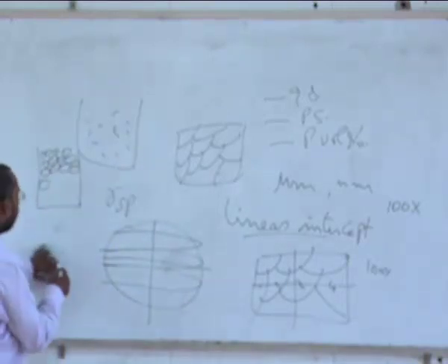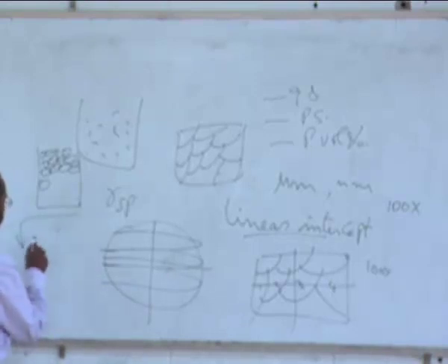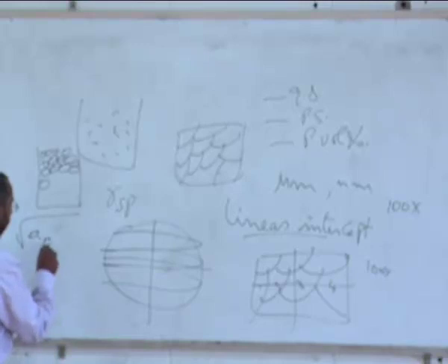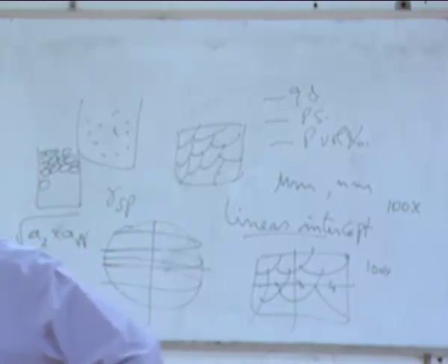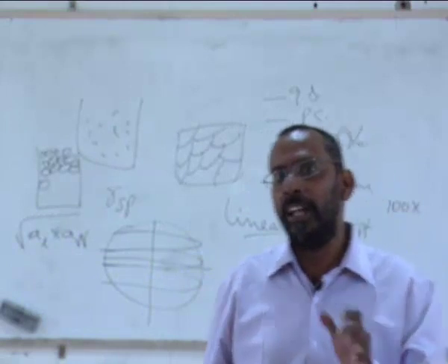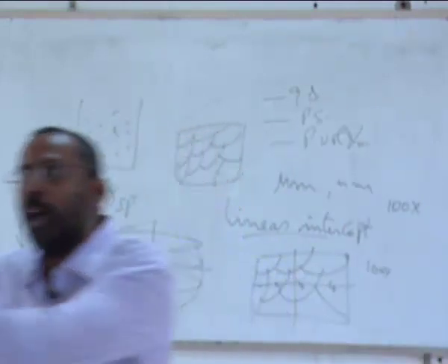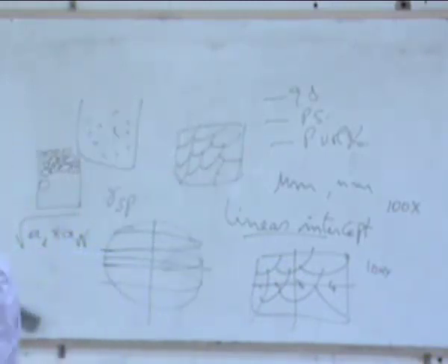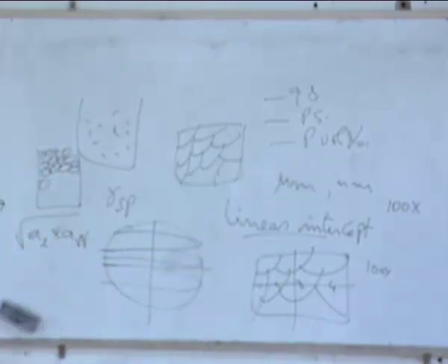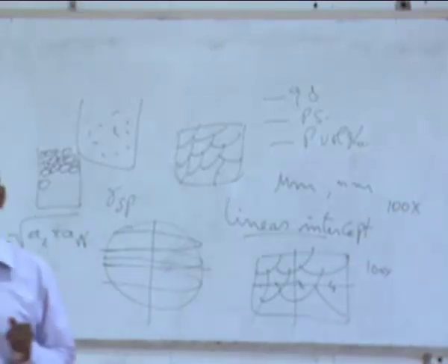Once you know the average length and average width, take a square root of average length times average width. So basically you are taking the area and taking a square root of the area. The square root of the area can be equated to a particular dimension. It is like equating a rectangular area to a square area. In a rectangle you have 2 dimensions, in a square you have only 1 dimension. So I am representing 2 dimensions as 1 single dimension, and whatever value you get as the square root is given as a grain size, if you want to give 1 single number representing that.